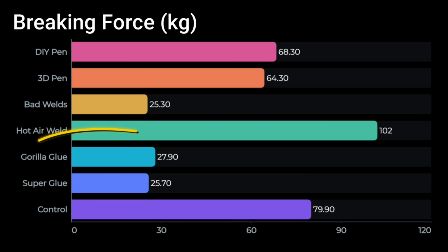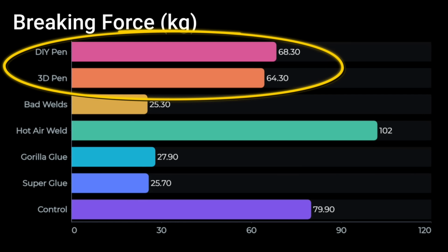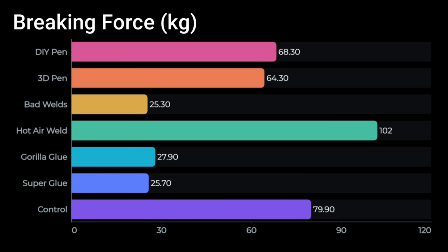So here are some interesting results. We can see the glued samples have a pretty low breaking force, but the properly welded samples for both our DIY pen and our off-the-shelf pen are just a little bit lower than the controls, so pretty strong in general. And our hot air sample is the strongest by a decent margin.